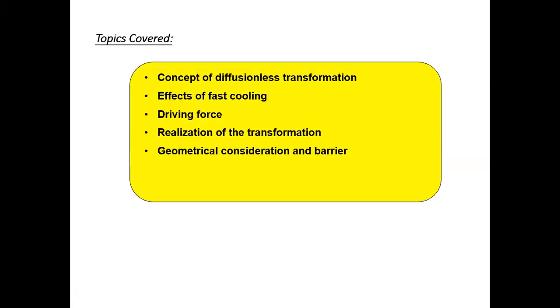that is not beneficial. There's no free lunch, right? Since there is a transformation, there has to be a way for nature to use this to reduce the energy. So there will be a driving force, and we'll see, if you're not achieving the transformation through diffusion, what is the pathway that you're going to realize this transformation through, right? And finally, we're going to consider the geometrical consideration of the barrier, because in this case there's no diffusion, right? So the barrier and the driving force are different from what we have already considered before. So that's basically an overview of what we can discuss. It's quite interesting. It's completely different from what we already know.